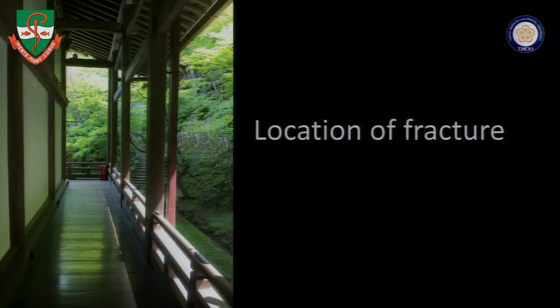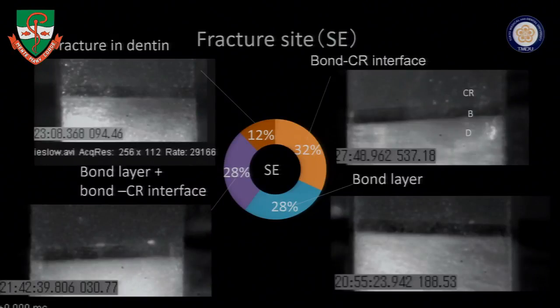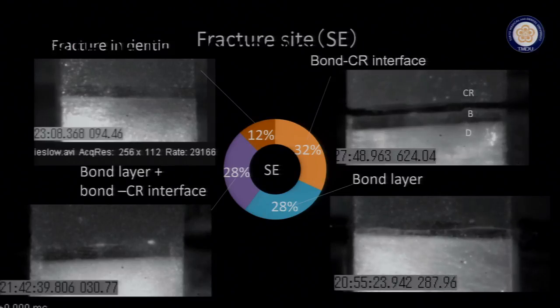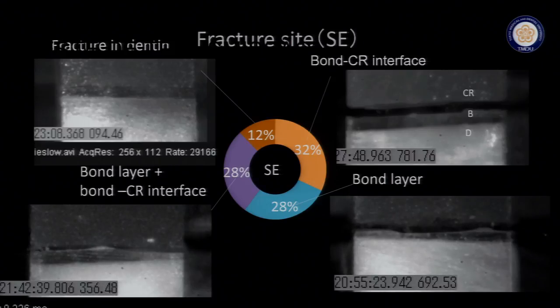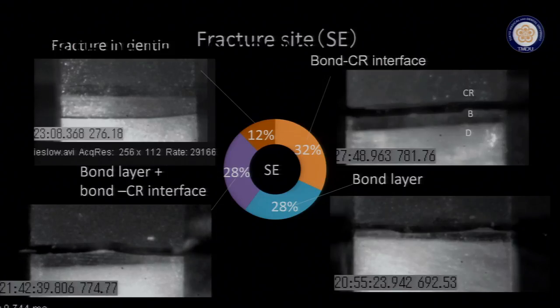Okay, we could summarize the location of the fracture. In case of two-step self-etching, the most frequent fracture occurred at the bond and composite interface. Look at this one. Okay. Of course, the initiation point was evaluated. And the second most frequent fracture occurred at the bond layer, in the bonding resin layer, like this. The same percentage, it is a mixture of this pattern. And 12% show the fracture in dentin. Okay. This is the result in case of two-step self-etching.